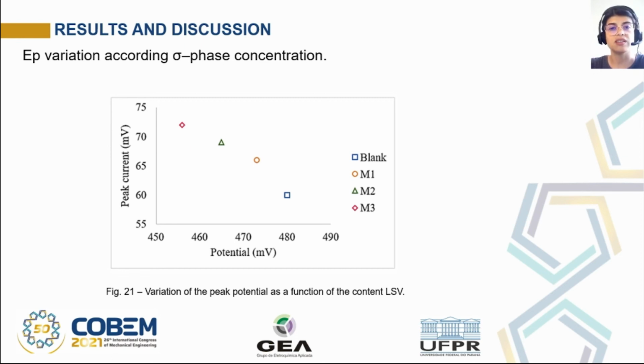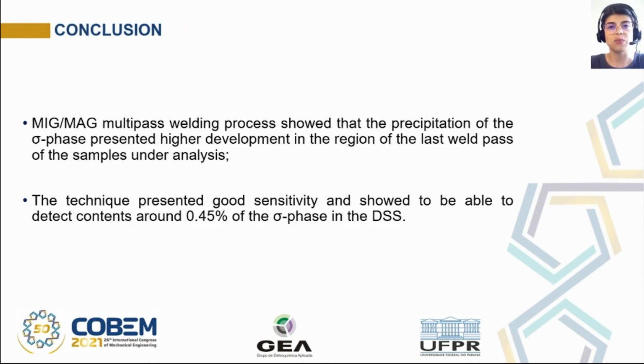This behavior can be explained according to the sigma phase concentration because this phase has chromium in its composition, and this element is very reactive, which favors the oxidation reaction on the surface of the DSS. So, in this work, we observed that in the MIG-MAG multipass welding process, the precipitation of sigma phase showed a higher development in the region of the last weld pass of the samples under analysis, and the linear sweep voltammetry technique presented a good sensitivity and was able to detect contents around 0.45% of sigma phase in DSS.